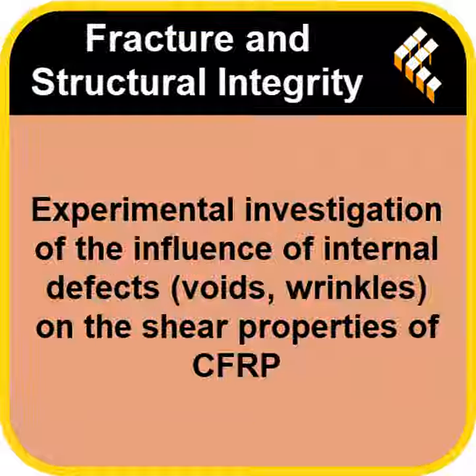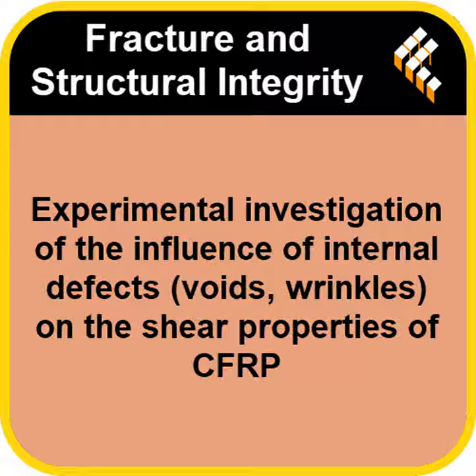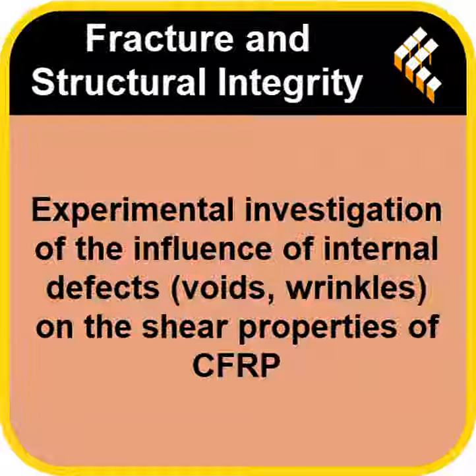Exactly. The localized waviness of the fibers actually added material bulk in that tested region. Stiffness, or modulus, isn't just about material quality. It's also related to geometry and how much material is resisting the load. So the increase in thickness in the wrinkled zone more than compensated for any local weakness or misalignment caused by the wrinkle itself. That's the explanation offered in the study. The structural effect of the added thickness dominated, leading to a higher overall shear stiffness measurement for that specific gauge section, even though the ultimate strength was slightly lower.